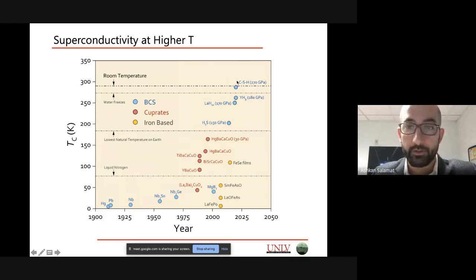And I really want to clearly state here, until about the 1970s, it was assumed you could only have superconductivity occur at ultra low temperatures. There was really a paradigm shift in the late 60s and early 70s that made us rethink coupling phenomena within these quantum states. And so this is the evolution of our material. This is all very exciting. We've been able to add a dot to this map here. More importantly, we also are about to publish our second work, where we have the second highest Tc of any material. And the idea is to really monopolize these materials over the next coming months.